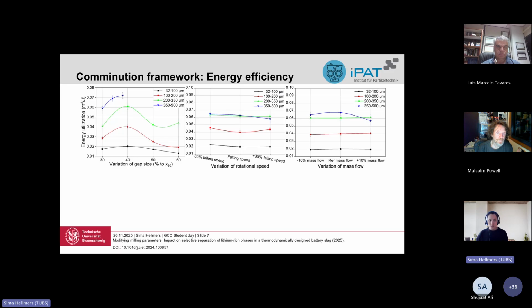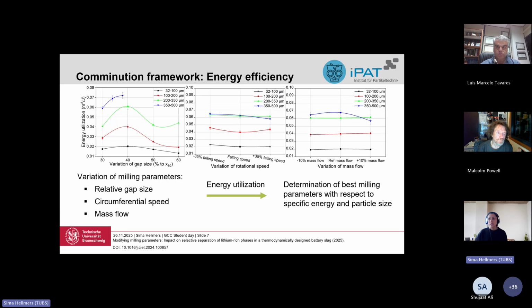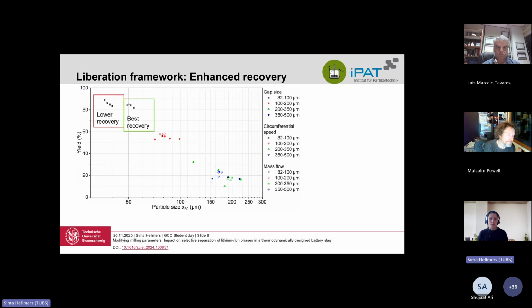So let's look at the different processes. What we can see is that energy utilization is the energy that we need to produce new surfaces. The higher it is, the more efficient our process is. There are 2 aspects that play a very important role in it. One of them is the feed size, and the other is the gap size relative to the feed size, changing from 30 to 60%. The mass flow and the variation of the circumferential speed did not play a very strong role in our energy efficiency. So what happened there? We produced different sizes and then fed them to the flotation cell to see which one was more efficient.